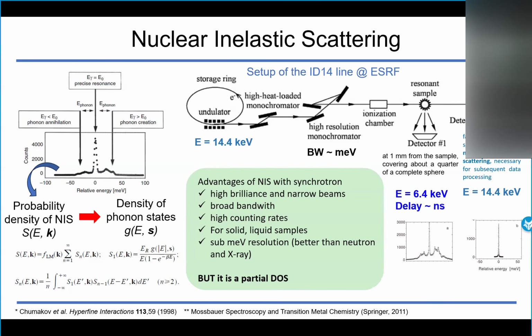Technically, nuclear inelastic scattering needs synchrotron light because we need a highly brilliant source and also the possibility to sweep a wide range of gamma ray energies. This is why we considered again the ID14 beamline in Grenoble. Like for the SMS, the 14.4 kiloelectron-volt gamma rays are selected. Then only the monochromators are used to have a bandwidth of the order of millielectron-volt, so broader than the one of the SMS. Then the gamma rays interact with the sample, and what is detected is the fluorescence. So gamma rays that now have an energy of the order of 6.4 kiloelectron-volt are emitted with a delay of the order of nanoseconds with respect to the interaction.